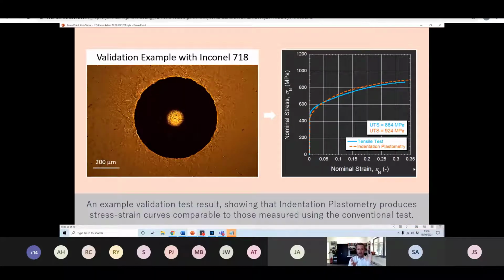Anyway, let's look at a validation example. Let's get to the core of this. What we can see with this particular piece of Inconel is a micrograph on the left-hand side showing one of those indents. You can see that it's a nice indent. One of the nice features actually is that when you use this technology, you indent a reasonably nice surface, the local microstructure reveals itself, and you can get a sense straight away as to what the grain features look like, what the grain size is, etc. It's a side thing, but it's very interesting nonetheless.